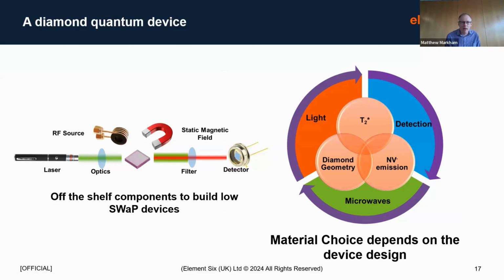That's a similar sort of frequency to what your mobile phone is operating at. You apply a static magnetic field, and then the green light basically stimulates this red photoluminescence. So you need a filter because you're just interested in measuring the red photoluminescence. That's your signal, and that peaks around 650 nanometers. So that means you can use a silicon photodetector.